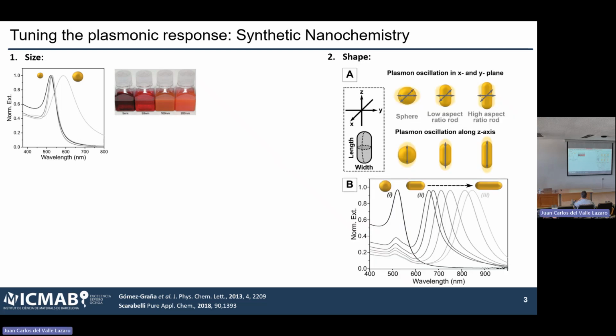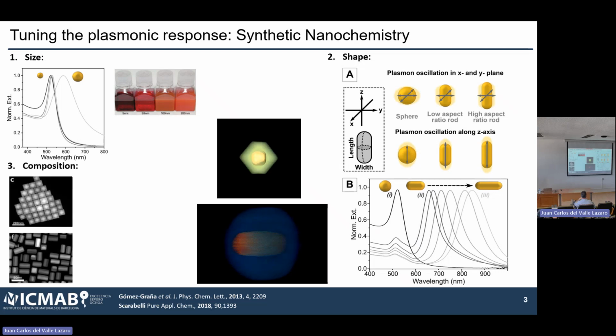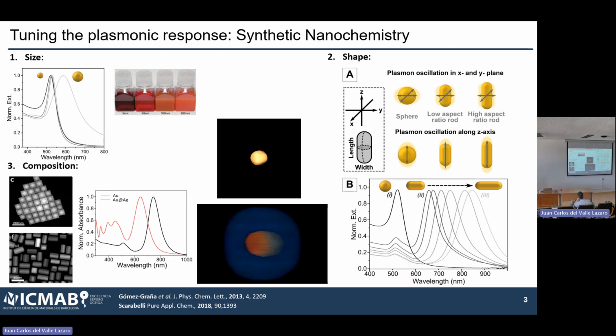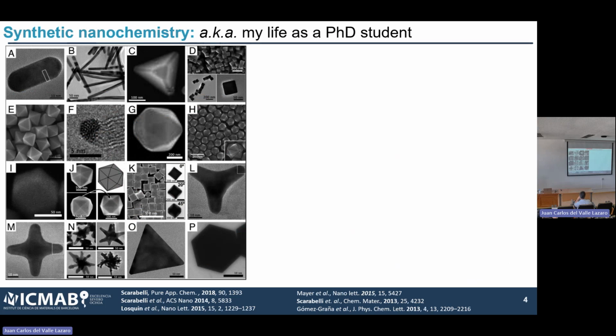For example, here you can see the case of the nanorods, which, being an elongated sphere, will have two types of response depending on the orientation of the nanoparticle with respect to the light: a longitudinal plasmon and a transversal plasmon. But we can also play with the composition, making bimetallic or multimetallic structures, and this will again change the optical response. So this can be summarized a little bit in the slides. That is basically my life as a PhD student.